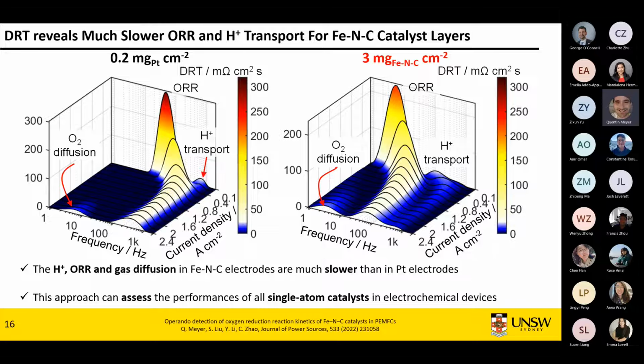Now, when you look at our PGM-free catalyst, we overall have the same kind of shapes, but quite different processes going on. Proton transport is much wider and at much lower frequencies. ORR happens much slower, probably about 5 to 10 times slower. And finally, gas diffusion looks overall similar, but still shifted towards lower frequency. The reasons this happens are multiple. First, proton transport will be far more challenging because you have a very thick electrode. Also, your protons have to go all the way within nanopores, whereas for platinum on carbon, the platinum is only on the surface of carbon nanoparticles. So there isn't this degree. Similarly, for the ORR reaction, you've got this whole problem over here as well of a much slower reaction for the same reasons. And gas diffusion will also be slowed down simply because of the structure and thickness of the electrode.